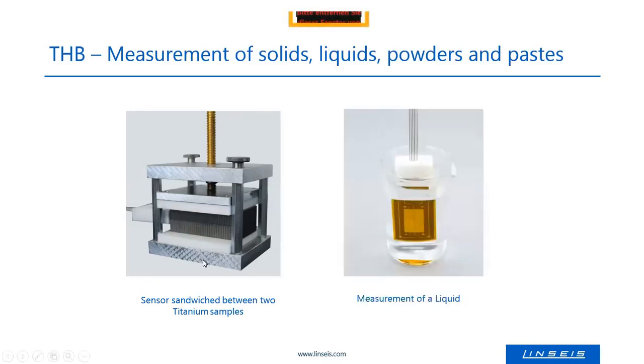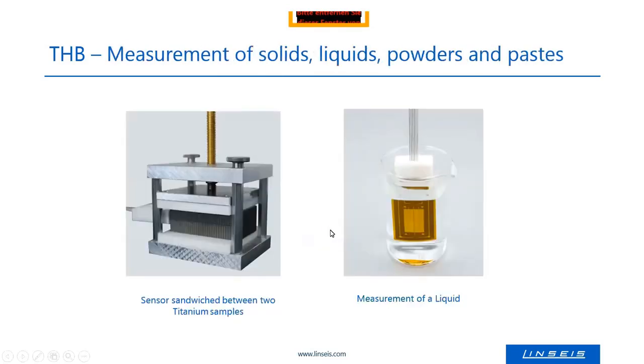For liquids, you can just put the sensor into the liquid. But we have also special sensors with a metal frame around it. If you have viscous liquids or pastes, powders, or loose samples, then you use a sensor like this, but with a metal frame around.